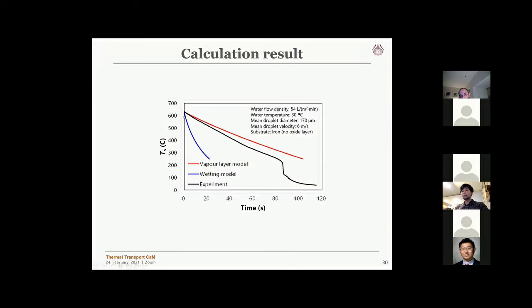And also we have this blue curve here. This is a heat transfer calculated using the so-called wetting model. This wetting model assumes basically there's no film layer between the droplet and the substrate. So this is just complete, direct heat conduction from the surface to the droplet.